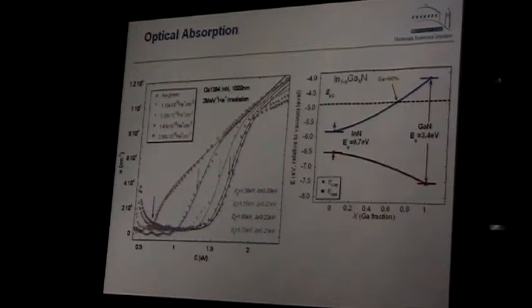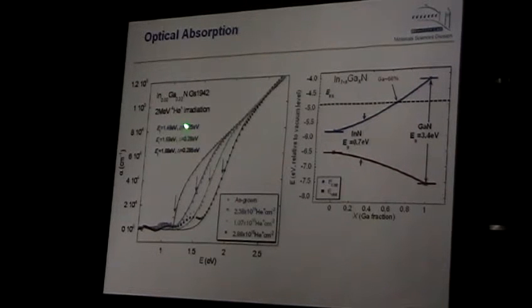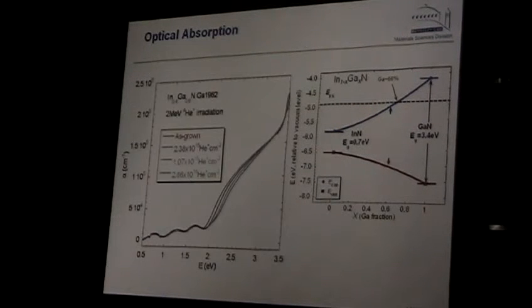So this is how it looks in indium nitride. We have this much shift, and we can shift it by irradiation that much. Now we go to a different composition. We have a sample now with 32% gallium, somewhere here. We expect less of a shift because it goes only from here to this stabilization energy. And in fact it does. And finally we go close to the crossover. Now the Fermi energy should not shift because it's almost saturated already. And in fact it doesn't. We irradiate very heavily, but the band edge remains unchanged.